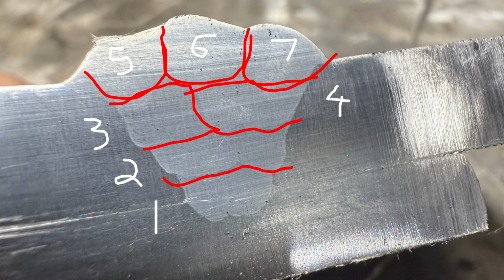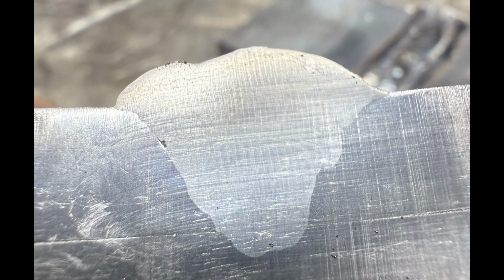Well, let's look at the other side of the cut and etch. This is where things get interesting. What appeared to be a possible lack of fusion on the other side of the plate is an actual lack of fusion on this side. And this is only about an 1/8 inch away, because you have to assume the saw blade cut plus the polishing and etching of it. And this is clearly a lack of fusion. This is going to be very common with the short arc MIG process on thicker plate.